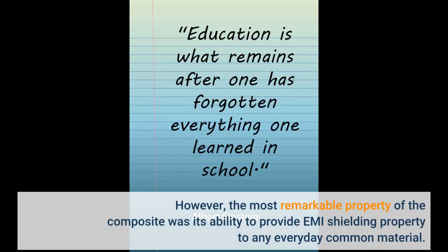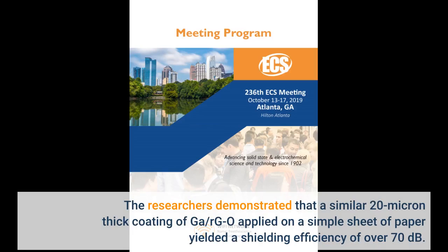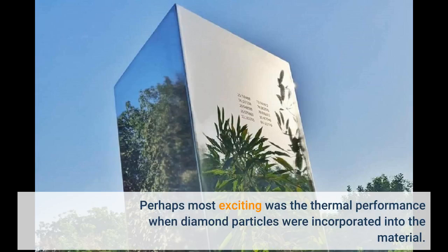However, the most remarkable property of the composite was its ability to provide EMI shielding property to any everyday common material. The researchers demonstrated that a similar 20-micron thick coating of Ga-RGO applied on a simple sheet of paper yielded a shielding efficiency of over 70 decibels. Perhaps most exciting was the thermal performance when diamond particles were incorporated into the material.